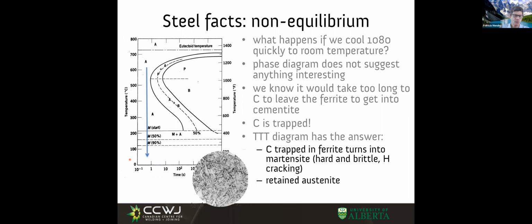And that's what happens when you cool down too fast. Low carbon steels, it's difficult to get martensite. High carbon steels, or steels that have alloy, they can get martensite quite easily. Some steels, no matter how you weld them, you're always going to end up with martensite - it's because they cool so fast that they reach this martensite transformation before they can start transforming.